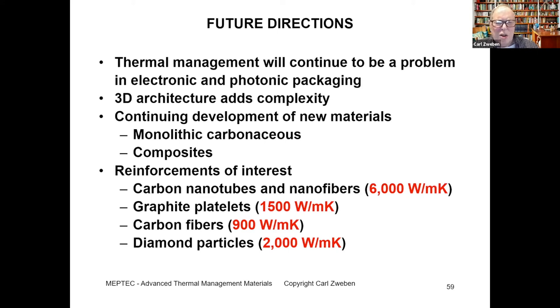Graphite platelets, I showed you a graphite platelet reinforced aluminum earlier. They have thermal conductivities as high as 1,500 watts per meter Kelvin. Carbon fibers, diamond particles, and as I mentioned earlier, diamond particles have thermal conductivities as high as 2,000 watts per meter Kelvin.